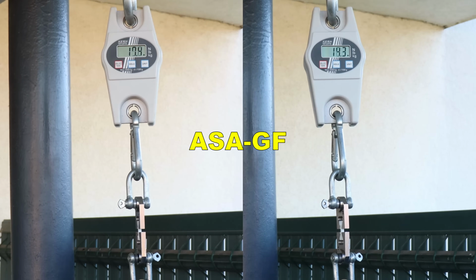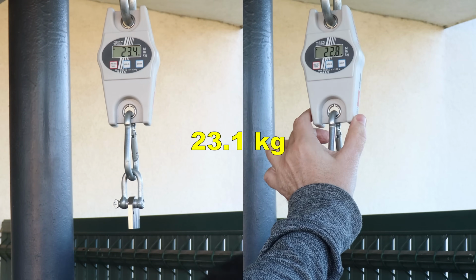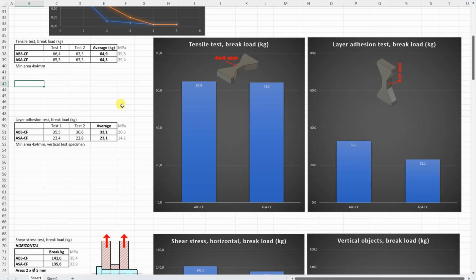ASA. Well, still acceptable. As most of you requested, analyzing the results immediately after the testing. On the tensile test, no big difference between these two materials, and they are very close to the average ABS and ASA tensile strength. On the layer adhesion test, well, the ASA is noticeably weaker, on the edge of acceptable,